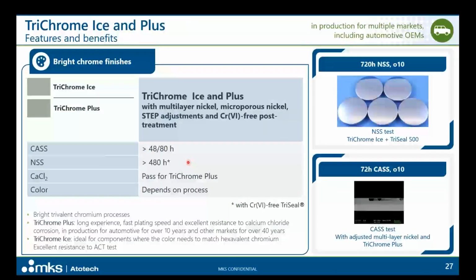So going a little bit deeper about the bright chrome finishes, as mentioned, and working with the right multi-layer nickel system, the Trichrome Ice and Trichrome Plus can offer excellent CASS results, excellent neutral salt spray results, in this case with the STEP treatment, and in the case of the calcium chloride test, the results with the Trichrome Plus are excellent. And the color, of course, Trichrome Ice and Plus will not offer exactly the same color. When the main goal is to match the color from the decorative hexavalent chrome, Trichrome Ice is the answer.